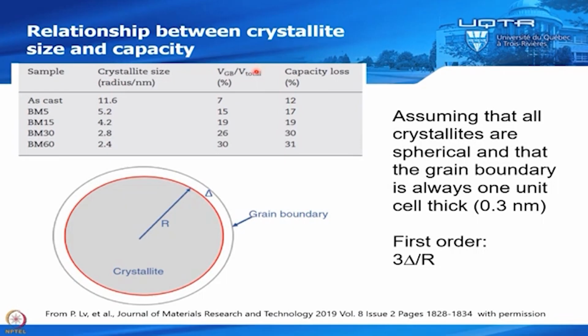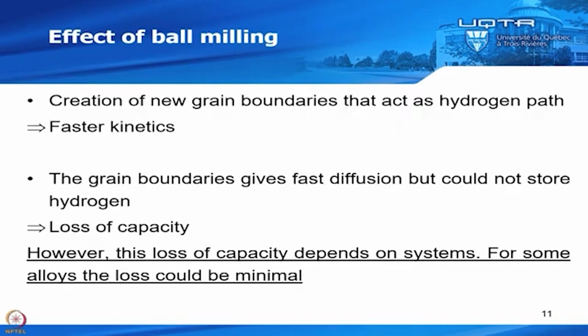Okay, so if you do that, you see that if you express the volume of the grain boundary over the total volume, these are with respect to the crystallite size. So these are the numbers, and that's the hydrogen capacity loss that we measured. And you see that these numbers are very close to these numbers. So it looks like the loss of capacity is scaling exactly as the total volume of the grain boundary.